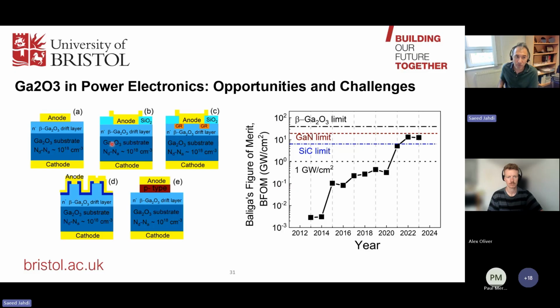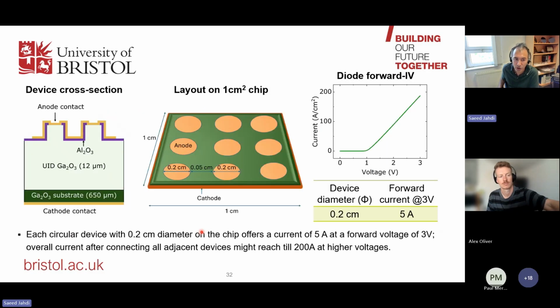And finally, we also do a little bit of work on gallium oxide too, as Paul was mentioning. They are doing the fabrication. We have a team in Bristol, Professor Martin Kuball, Dr. Matthew Smith, and the team also fabricating the gallium oxide devices. There are multiple structures that you can make the devices, and basically the bottom line is that we are trying to go to the beta gallium oxide limit to improve even the performance beyond what silicon carbide and gallium nitride can achieve. They have already fabricated some earlier stage chips.